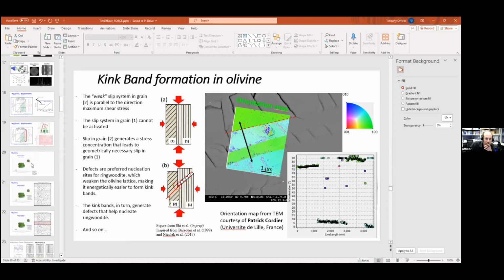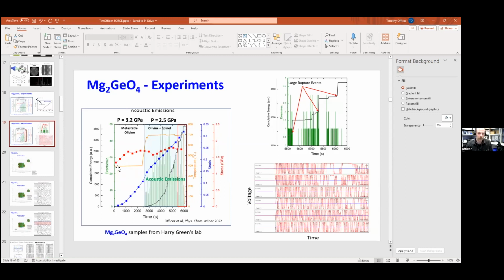In some sense, you can't necessarily know for sure, but the reason I think it is, if you look at this plot here, when we're deforming it at low temperature, so the olivine's metastable, we don't generate the high pressure phase, and we don't see any acoustic emissions. So it seems reasonable to believe that once we generate the high pressure phase and start seeing acoustic activity, it's probably from the phase transformation, not from slip that occurs and then the phase transformation just happens in that place. Does that make sense? Yes, that does. Thank you.